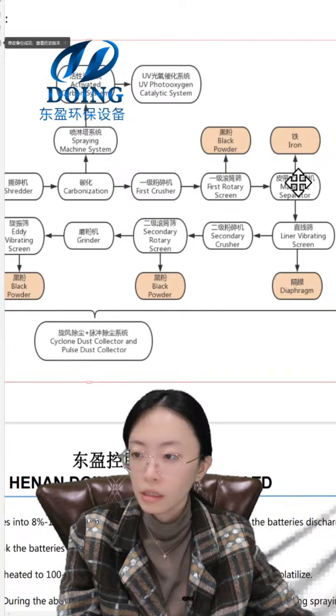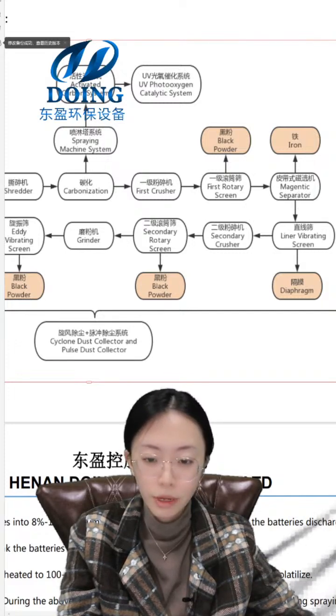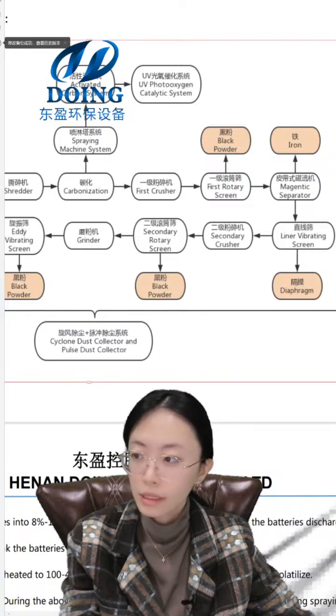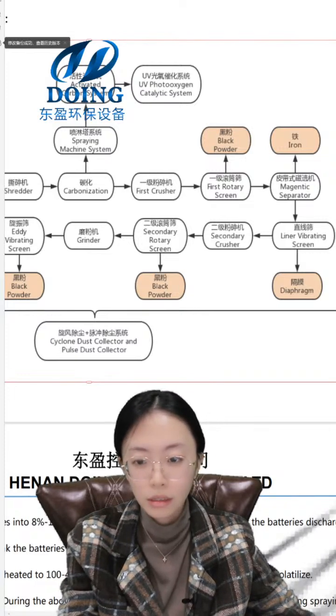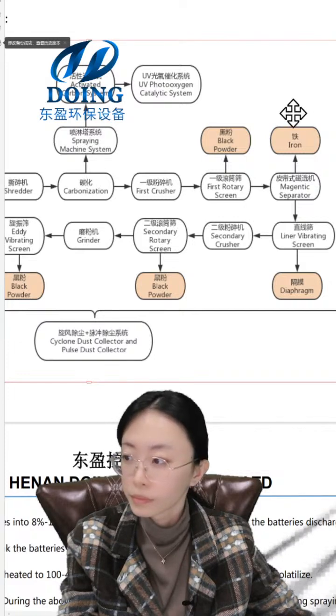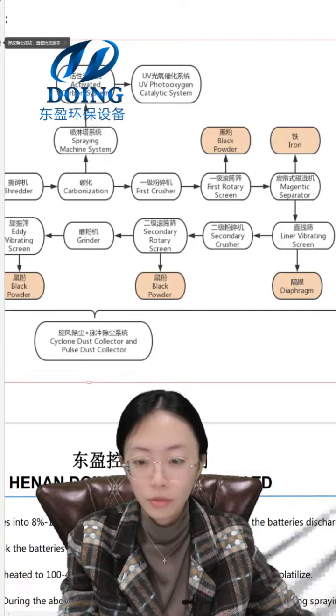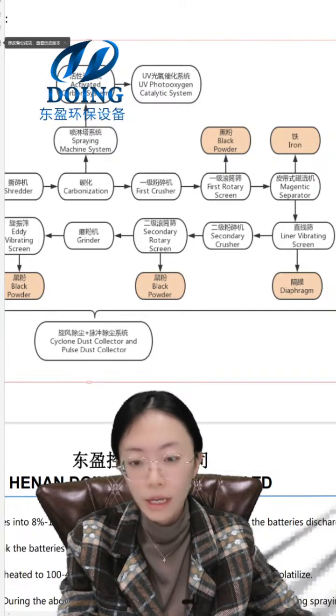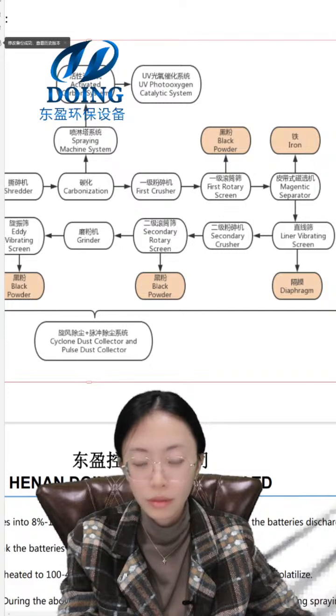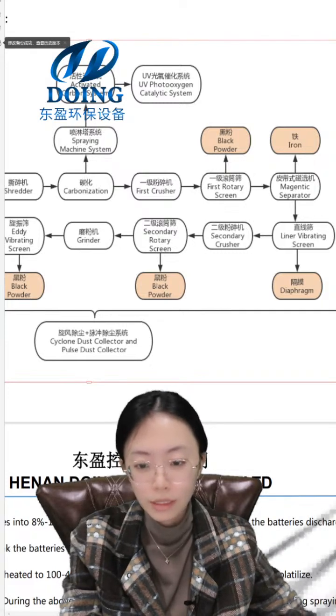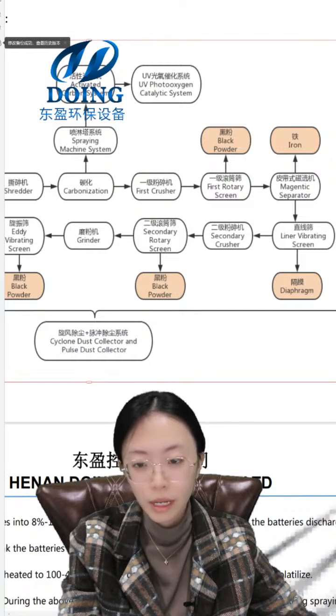And then this is the magnetic separator to separate the iron. And then it comes to the linear vibrating screen. The linear vibrating screen uses vibration for the screening. This step separates the black powder and the diaphragm inside, which is the plastic. So the linear vibrating screen will have 2 layers in this step. One is 2 millimeter, and the second is 100 mesh.